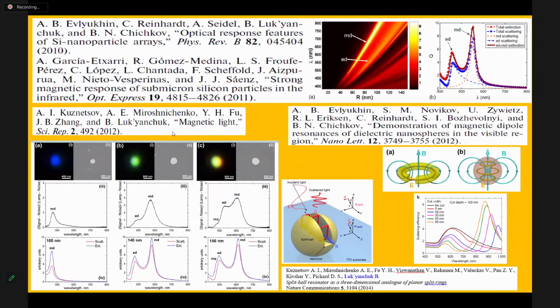So in 2010, two groups published a paper that it is possible to create huge magnetic moment even with small particles. It is necessary only to have sufficiently big refractive index, for example, refractive index higher than 2. And this theoretical prediction was quite fast checked experimentally. Also, a few groups showed that, except for electrical dipole, you can create magnetic dipole.